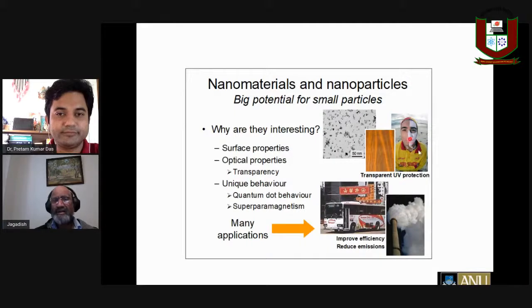So if I say I'm not interested in sunscreen, where else can I make use of this? For example, wood gets degraded whenever it's exposed to sunlight because of the UV radiation. If you incorporate nanoparticles of zinc oxide or titanium oxide of the right dimensions, they can absorb the UV light but allow the visible light to pass through, so the wood could be protected for a much longer period. People have also been trying to use nanoparticles of catalyst materials, because of their large surface area, in fuel tanks, and they enhance the catalysis quite significantly. That means the amount of petroleum used is much less, so you're also reducing greenhouse gas emissions.